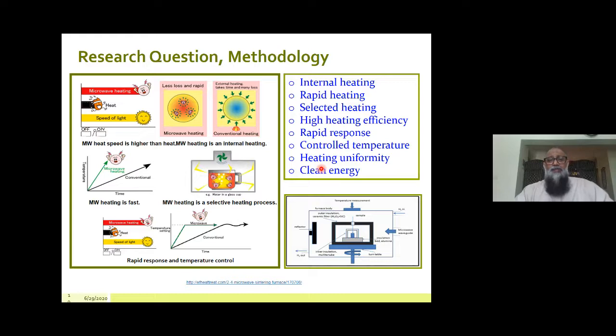The outstanding feature of the microwave sintering approach is that the sintering time is much less compared to the conventional sintering process. For example, in the conventional sintering process, the sintering time is usually in hours, 3 hours, 4 hours. But in microwave sintering, the time is only 20 minutes, 30 minutes. In our case, a sintering time of 30 minutes was employed.